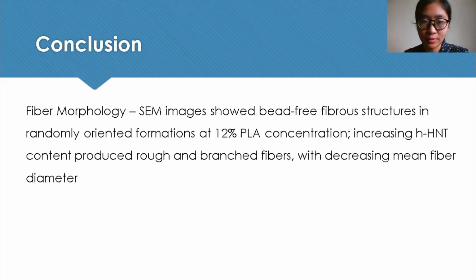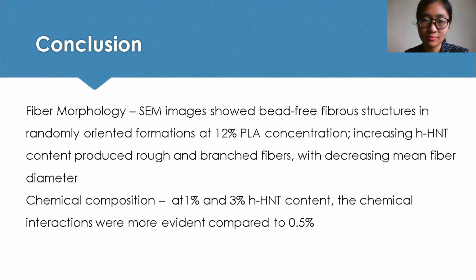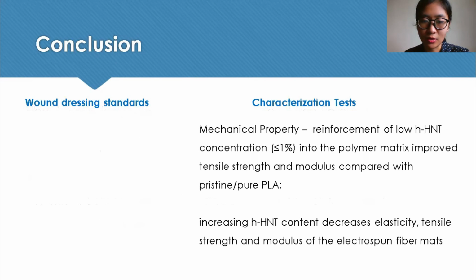So the fiber morphology of the pure and composite fiber mats was good. Some images showed bead-free fiber structures in randomly oriented formations, which was also desired in many published papers. And FTIR results also revealed successful interfacial interaction between the hydroxylated clay and the polymer matrix. At 1% and 3% HHNT content, the chemical interactions were more evident compared to 0.5% HHNT content. Consequently, the reinforcement of low HHNT concentration, less than or equal to 1%, into the polymer matrix improved tensile strength and modulus compared with pristine or pure PLA. So we can say that the conformability is good at 1% HHNT content.